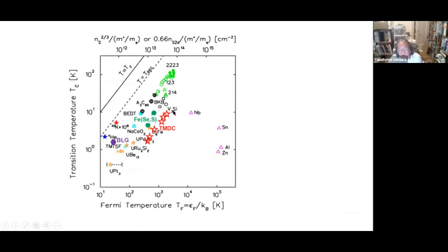Finally, this is my last graph. We have been showing mostly this highest TC case, but there are many systems showing this nearly linear relationship, but with much higher superfluid density. For example, transition metal dichalcogenide with various pressure, and iron selenide sulfide is here. Many materials show this sort of linear relationship. I think this is not coincidence, but there should be some fundamental reason. One of the reasons may be that this system, for example, has a multi-band effect. So it is encouraging us to think about why so many systems just show this linear relationship.